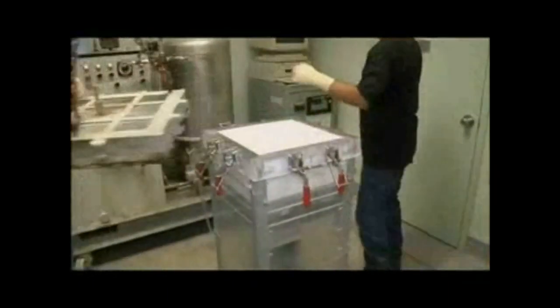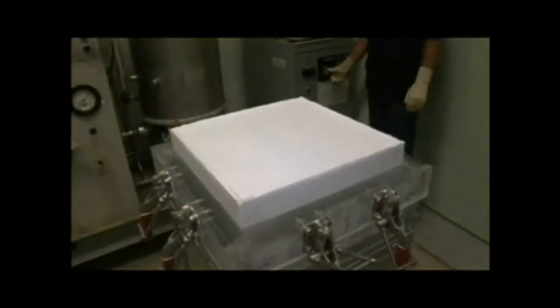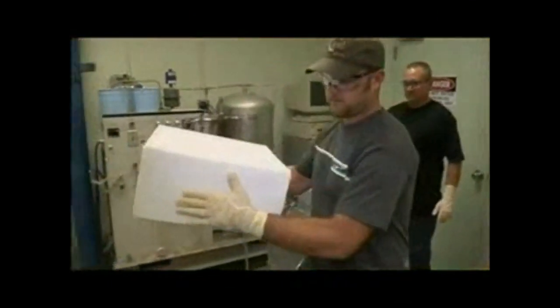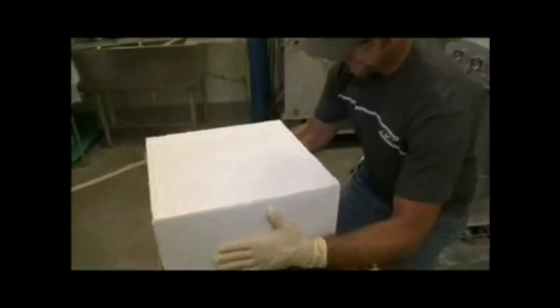At this stage of the process, the billet's been pressed. The next step is to actually extrude the billet out of the tower. At that point, it'll be taken to the other end of the building, dried for 16 hours at 250 degrees, and then ultimately fired in a kiln at 2,450 for several hours, and that will give you the block that I showed you to start off with.